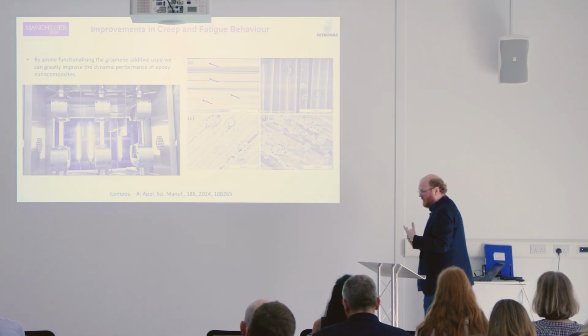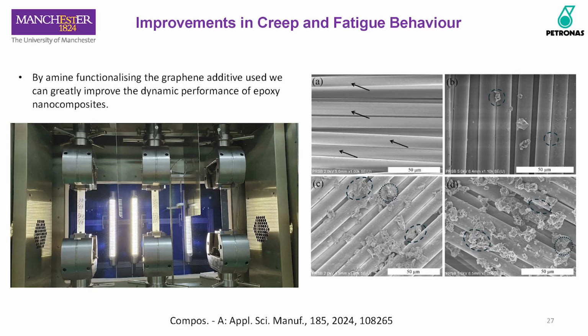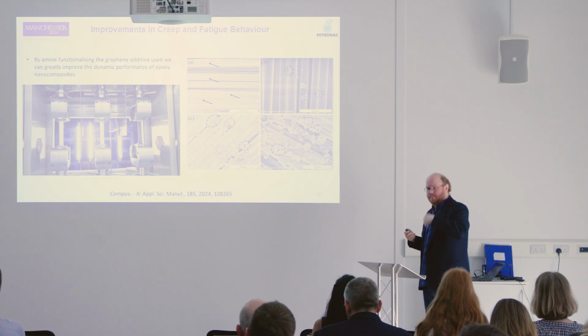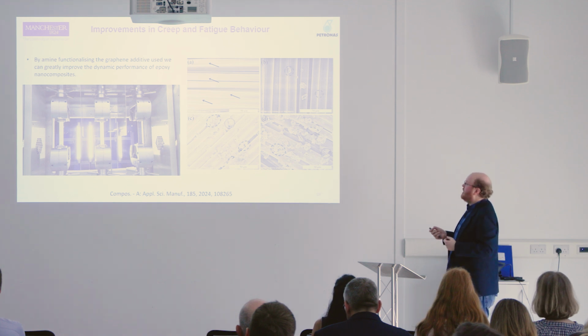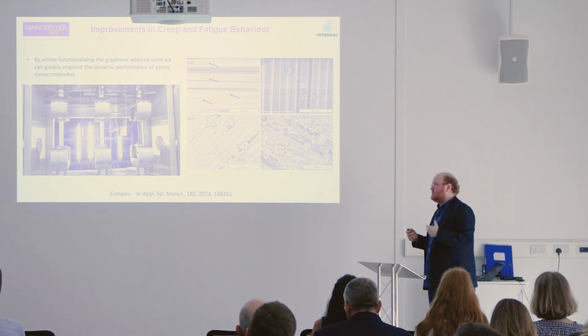The other area where we see a lot of benefits or a lot of improvements is in dynamic measurements. There are thousands and thousands of papers out there on mechanical properties of graphene composites. Typically, they're only looking at static measurements, where they do a single stress-strain curve, but they're not looking at, say, creep, where you have a continuous load over a prolonged period of time, or fatigue, where you have a cyclic load being applied again and again and again. So again, this was work that was sponsored by Petronas.